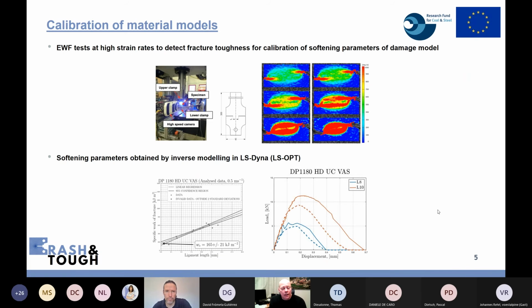And the next one is about how to calibrate the softening parameters in the GISSMO model. In this case, we have run similar experiments as David presented in the first session. It is the so-called essential work of fracture test, but in this case at very high strain rates. Once again, we are using our high-speed tensile testing machine, and the specimen geometry is still the double-edged notch.